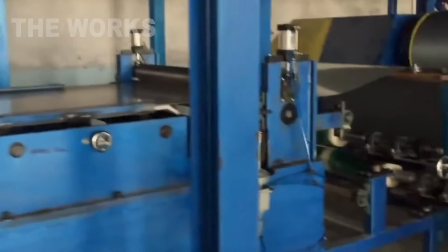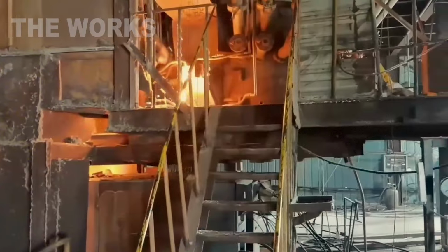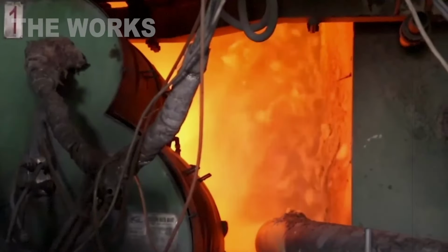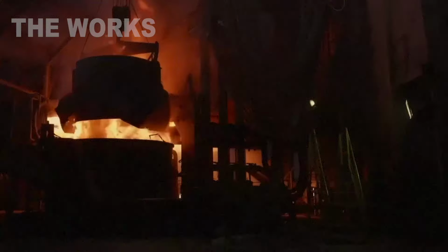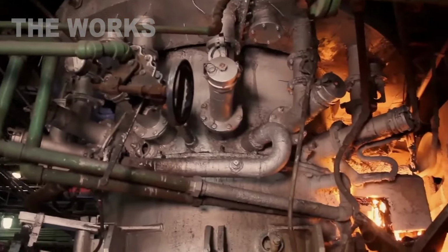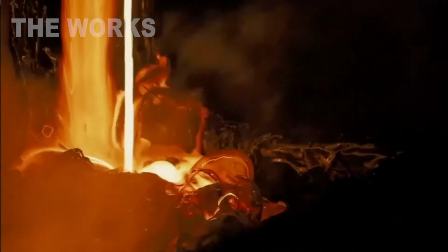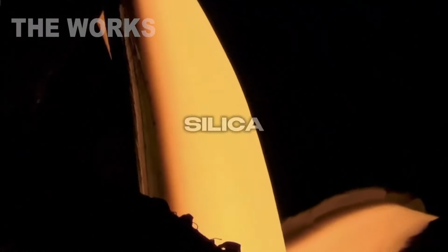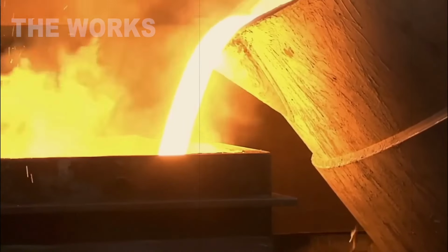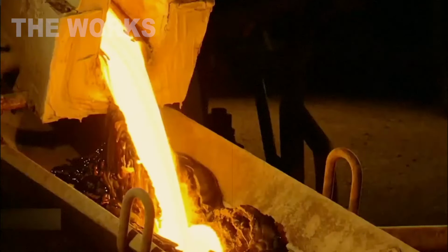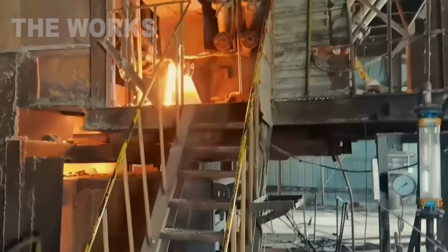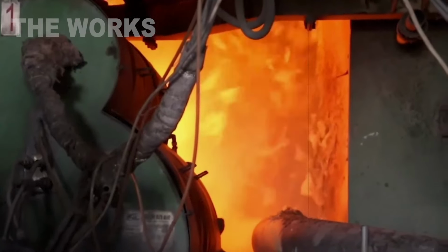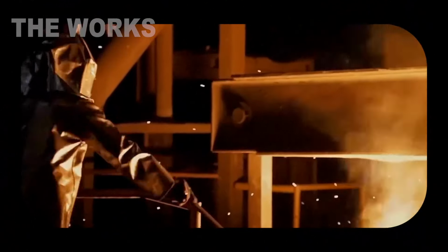Next comes the melting stage. The basalt and coke mixture gets fed into a massive furnace where temperatures climb above 2,700 degrees Fahrenheit. Under this intense heat, everything dissolves into a glowing red stream of lava rich in silica, aluminum oxide, calcium oxide, and magnesium oxide, transforming into a thick liquid almost identical to volcanic magma. When the molten stream pours out, sparks fly in every direction, and workers in ceramic fiber suits and metal masks step forward to check working conditions.